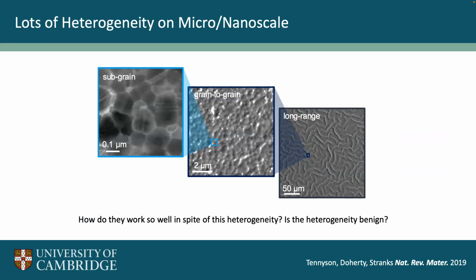One of the quite interesting things with these materials, and I alluded to it earlier, is that we see lots of disorder in these materials. And this is quite interesting. These are different electron microscope images zooming in gradually to higher and higher resolution all the way to here. And what we see is on all the different length scales, we see disorder. We see lots of variations. So this is really zoomed in here. You can see even a lot of these grains we find are actually made up of smaller subgrains and smaller crystallites. And again, this really opens the fundamental question: why do these work so well, even though they are so disordered and so heterogeneous in their properties? It's a very interesting question. It's still ongoing, I'd say.